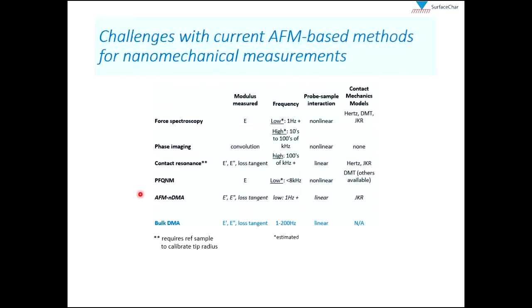So here is a summary of the challenges with current AFM-based methods for nanomechanics. Here are the techniques that I mentioned: force curves, phase imaging, contact resonance, PeakForce, and then the new entry to this field, AFM-nDMA, that is a focus of today's webinar. And then down here I have bulk DMA, which is what we're ultimately comparing to. So if we look at the modulus that is measured, and then the frequency space, whether we have a linear or nonlinear probe-sample interaction and what models are used, we can see the space that bulk DMA resides in. So very low frequency, a linear probe-sample interaction, obviously no contact mechanics models, and then see how these other techniques line up and compare with these bulk DMA measurements that we're ultimately going to be comparing to.